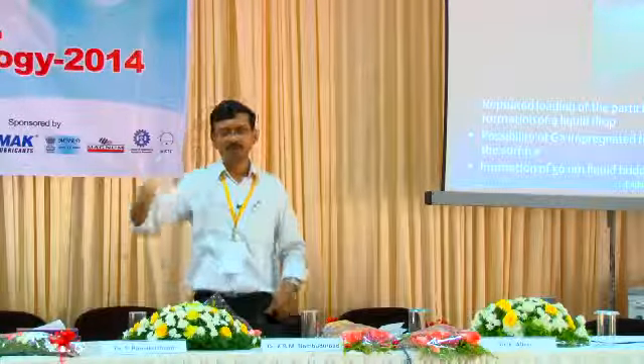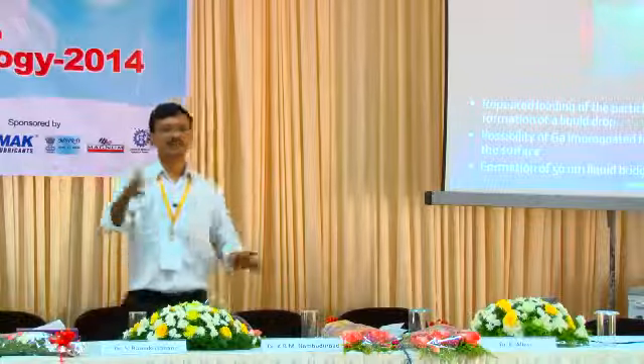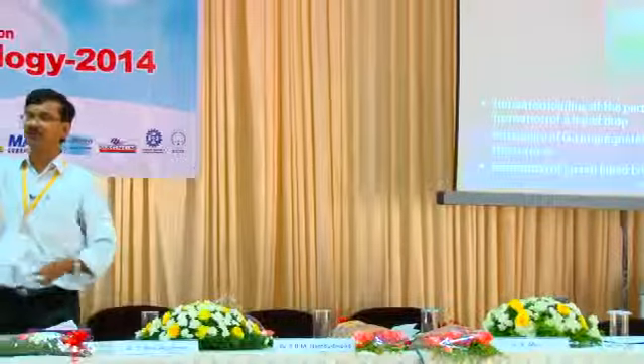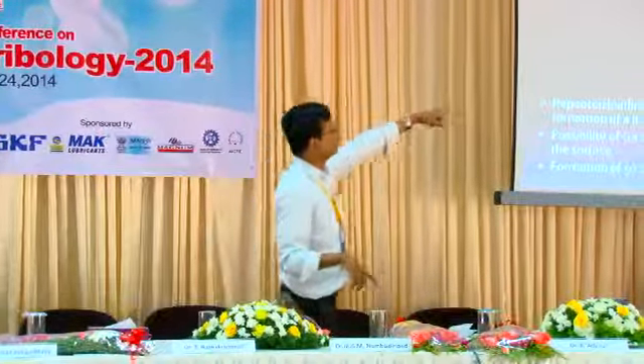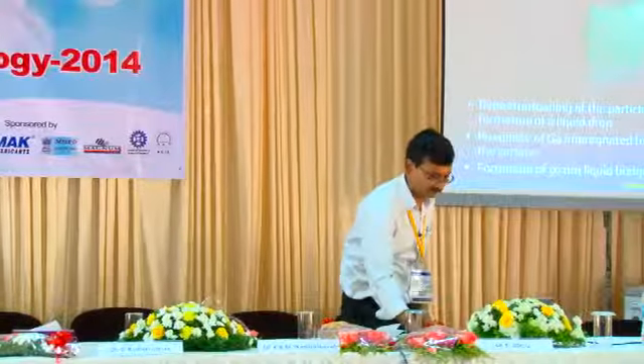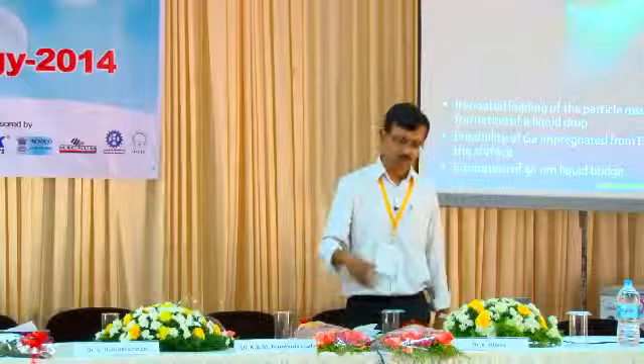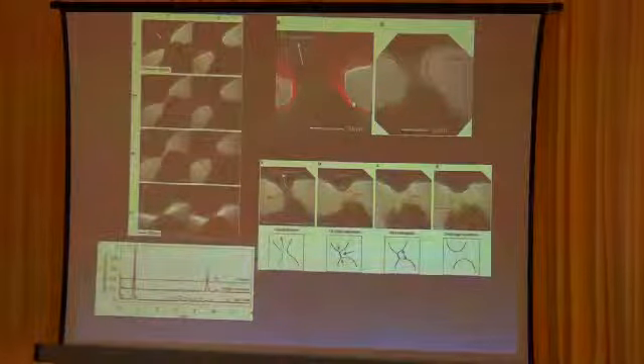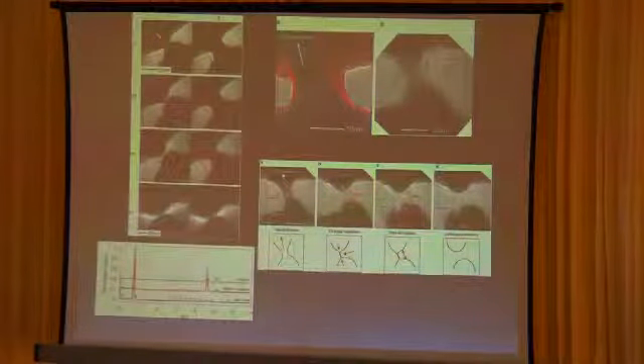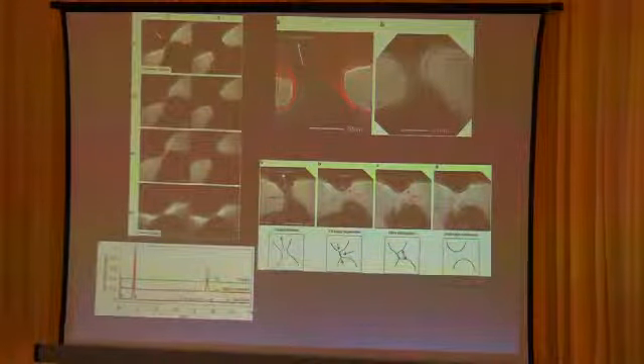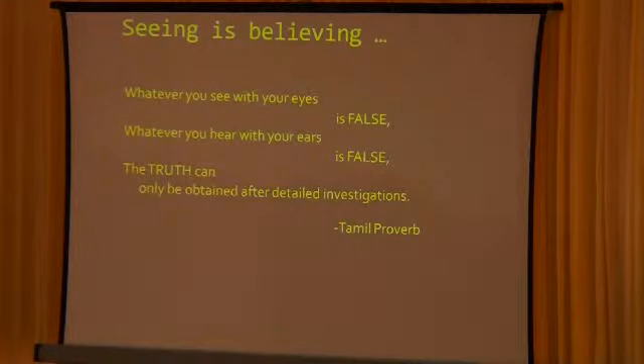So we have done energy loss spectroscopy in TEM which confirms that that droplet is rich in gallium. It may be some gallium aluminium alloy or only pure gallium, we don't know. This tells us how the liquid bridge is breaking at different points. We can measure viscosity. I think I'll end with this.